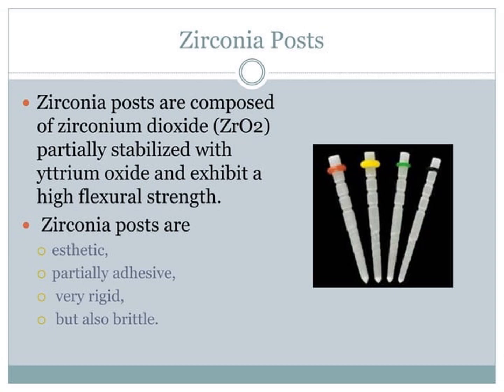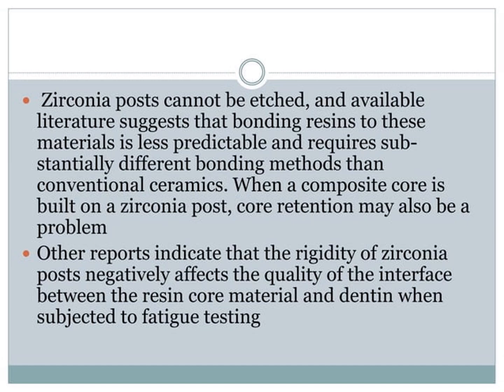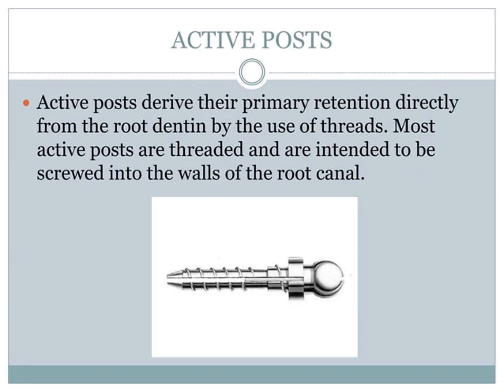Zirconia posts are composed of zirconium dioxide partially stabilized with the yttrium oxide and exhibit a high flexural strength. Zirconia posts are aesthetic, partially adhesive, very rigid but also brittle. Zirconia posts cannot be etched, and available literature suggests that bonding resin to these materials is unpredictable and requires substantially different bonding materials than conventional ceramics. When a composite core is built on a zirconia post, the core retention may also be a problem. Other reports indicate that the rigidity of the zirconia posts negatively affects the quality of the interface between the resin core material and dentin when subjected to fatigue testing.